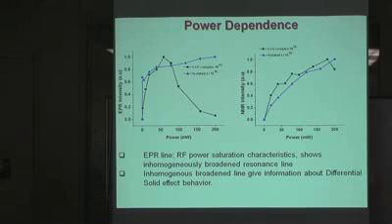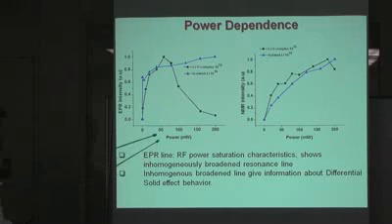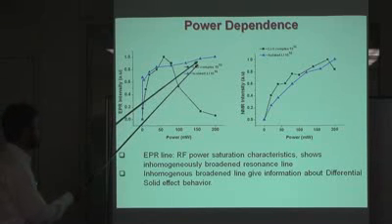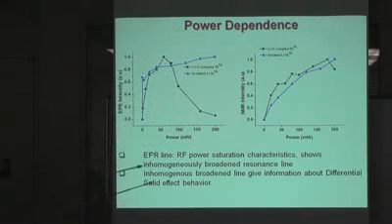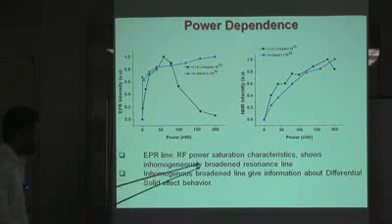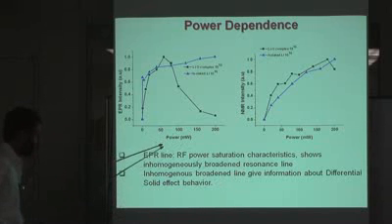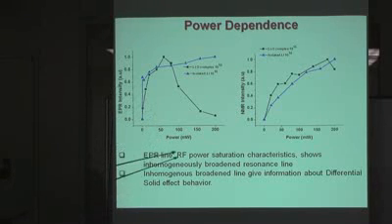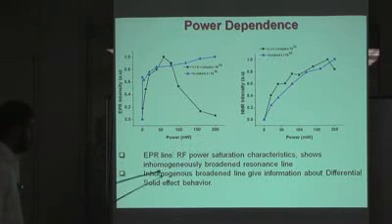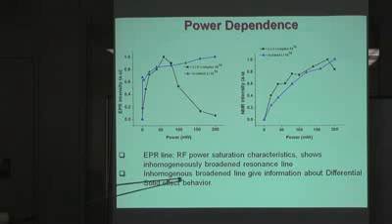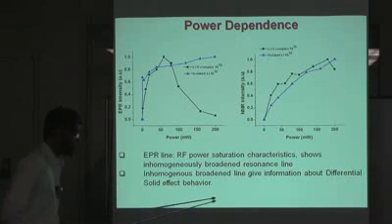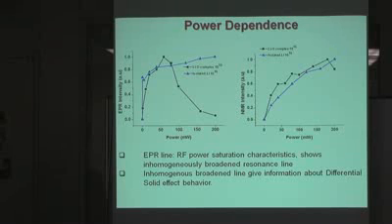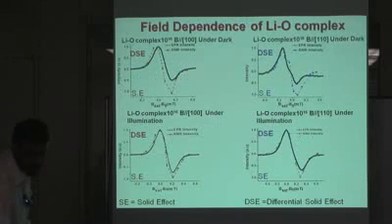Now, power dependence. Here, both samples, isolated lithium and lithium oxygen complex, show inhomogeneous broadening behavior when we saturate our EPR line. Inhomogeneous broadening gives information about the differential solid effect. Now I will show you my field dependence data.